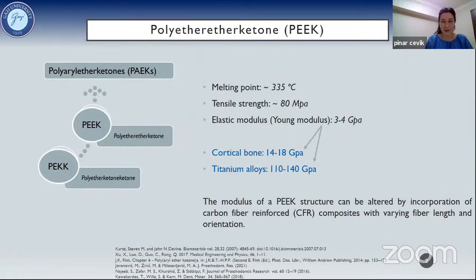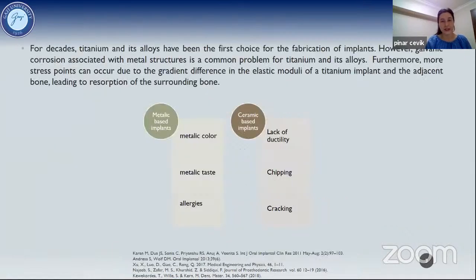And yes, the elastic modulus of PEEK is 3 to 4 gigapascal, which is very close to cortical bone as compared to titanium alloys, as you can see here. And also the modulus of PEEK structures can be altered by incorporation of carbon fiber reinforced composites with varying fiber length and orientation. For decades, titanium and its alloys have been the first choice for the fabrication of implants. However,